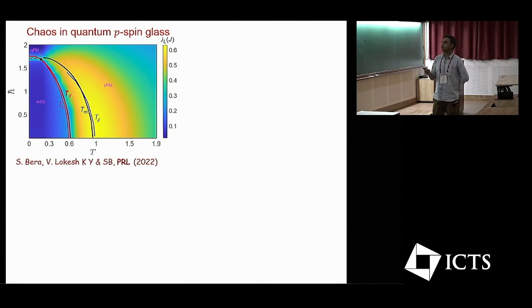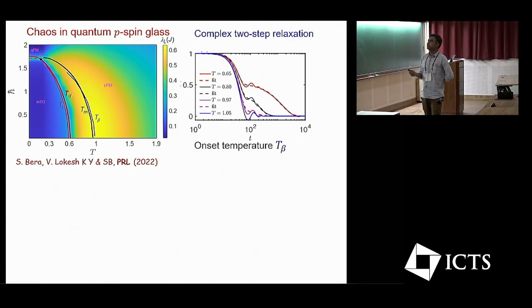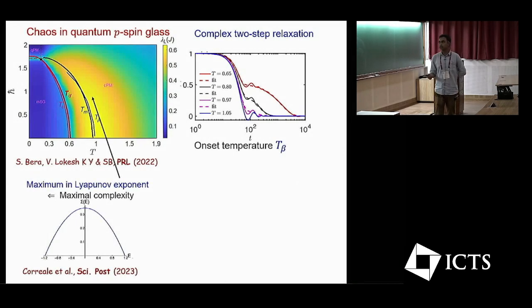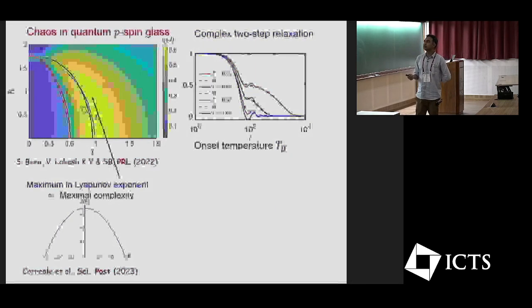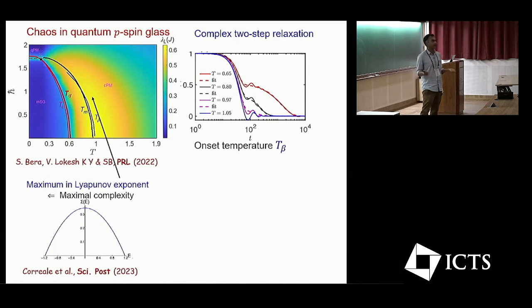However, if you look at lambda L, it actually has a maximum, which is indicated by this color, above the glass transition temperature, somewhat above it. In fact, what we showed is that exactly at this temperature you start getting the two-step relaxation, so this temperature exactly coincides with the onset of two-step relaxation. And later works showed that if you calculate the complexity of this potential energy landscape, basically you count at that temperature how many stationary points you are sampling, that also peaks at that temperature. So that means where you are sampling many more of these stationary points, there your chaos becomes enhanced.